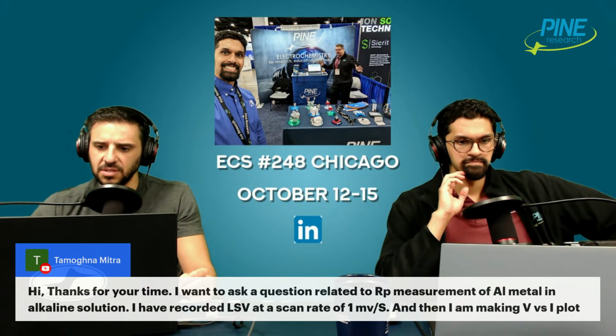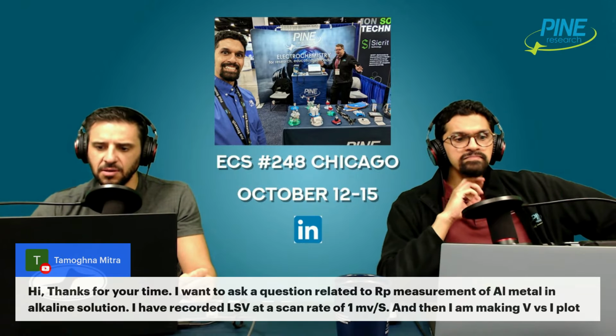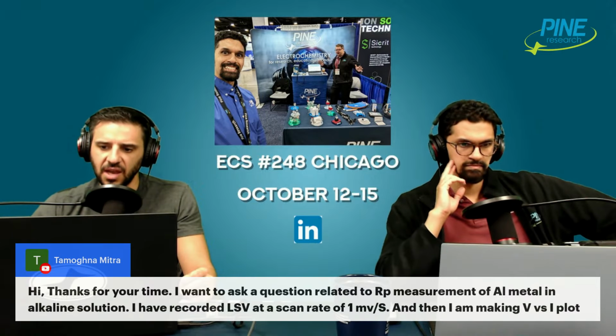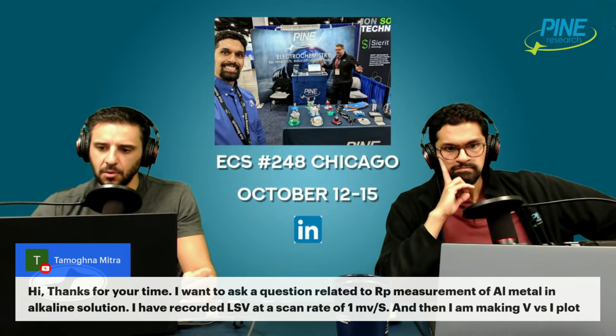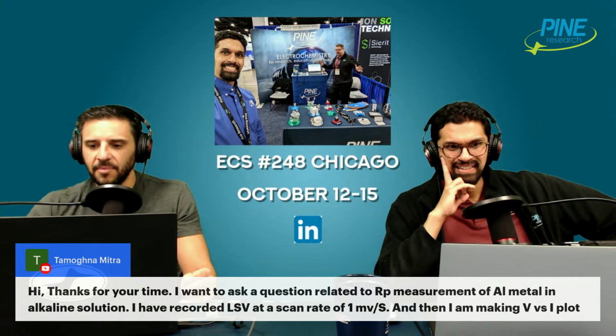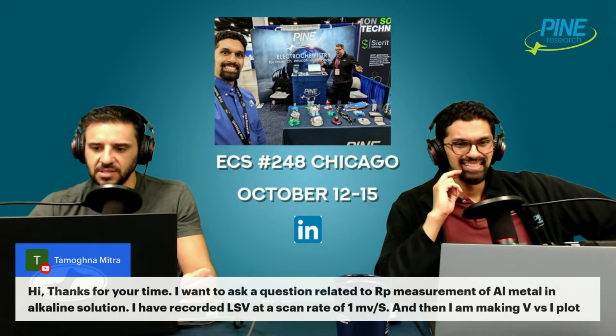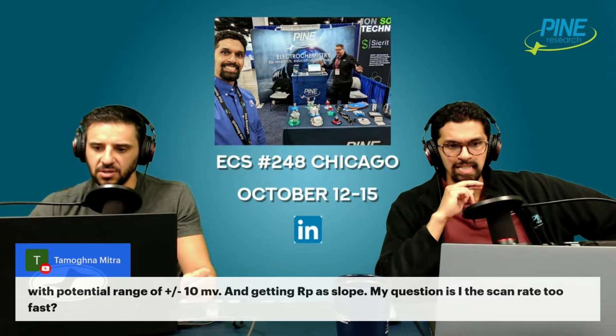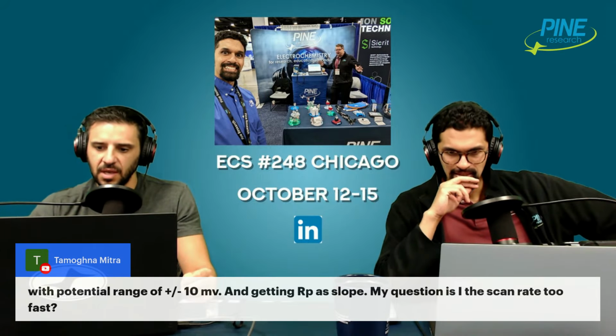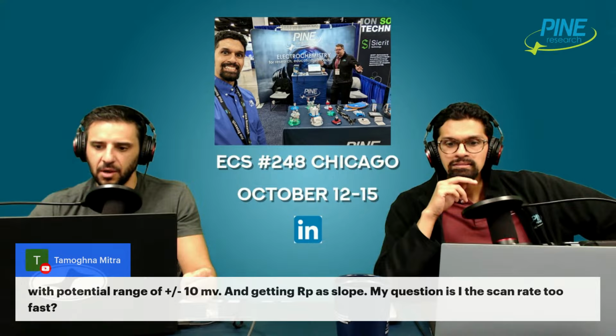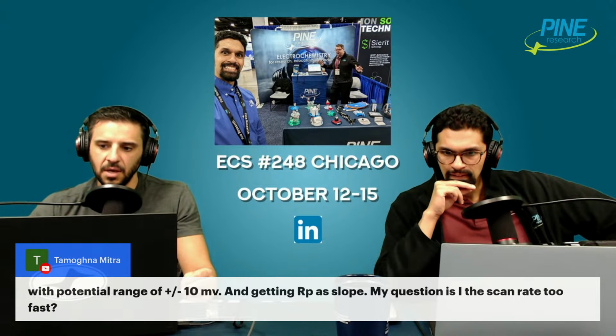Okay. That was good. Tamungna has a series of questions. I'll kind of look through this, and I think the answer is actually relatively straightforward, in my opinion. So, hi, thanks for your time. I want to ask a question related to RP, so it's polarization resistance, measurement of aluminum metal in alkaline solution. I have recorded an LSV scan at 1 millivolt per second, and then I am making a V versus I plot with potential range of plus or minus 10 millivolts and getting RP as a slope. My question is, is the scan rate too fast?